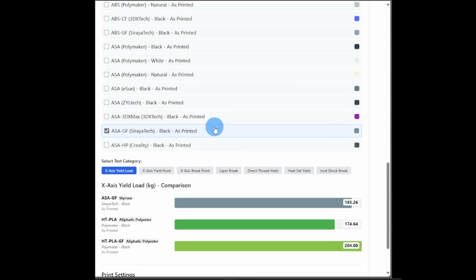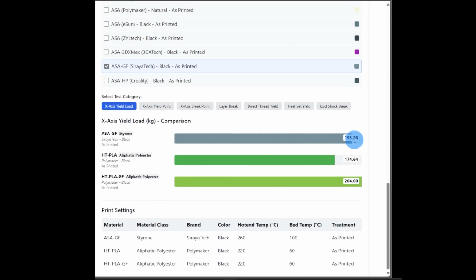it's an ASA glass fiber. So there's your ASA glass fiber, x-axis yield. Your high temp PLA glass fiber, x-axis yield. Do I need to say more on that one? This is just how far they stretched before they yielded. Breaking point. Layer adhesion. Well, PLA beat ASA glass fiber on layer adhesion, both ways. Direct thread, high temp PLA glass fiber. Heat set, the high temp PLAs beat the ASA glass fiber. Izod shock, well, one under, one over, all right in the same range.